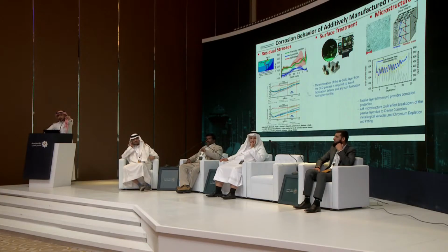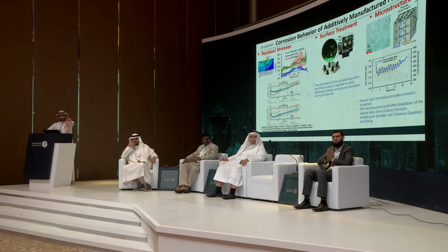The goal, you see the picture here under residual stresses. There are two pictures. The goal is to maintain the compressive residual stresses. While maintaining them, in the picture beside it, what I want is to have the compressive residual stresses in the negative region. The reason I want it in the negative region is to resist the corrosion behavior. And that's what we are projecting. The picture below it is the residual stresses along a couple of cycles. On the right side, we did a mapping for the microstructure and the grain. And this is what we are aiming for.